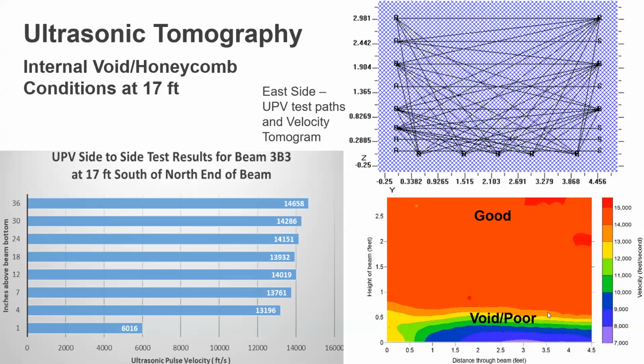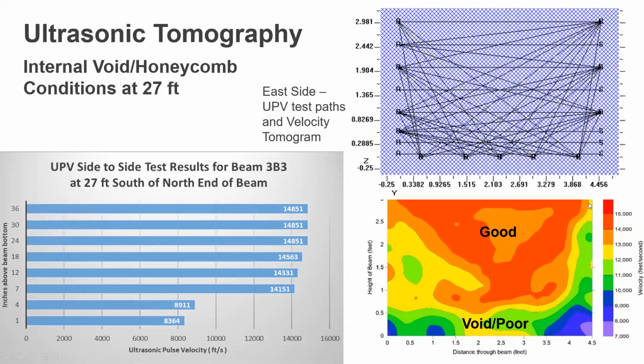So how does that look in the analyses of the tomogram? Well, you can see where it's good, much of it's good, but the bottom 9 inches to the bottom is in void and poor conditions, and particularly slow right at the very bottom. And that's reflecting and showing that, okay, you're gonna have to repair the bottom portion of this, but it's good above it.